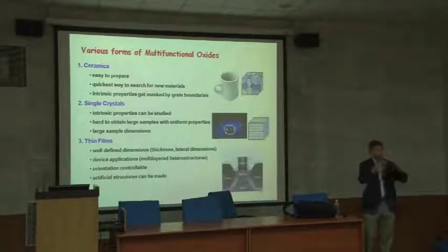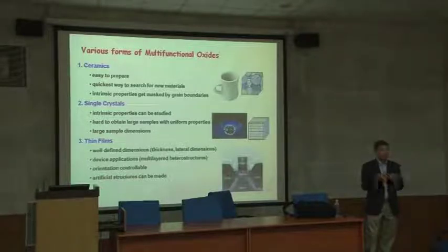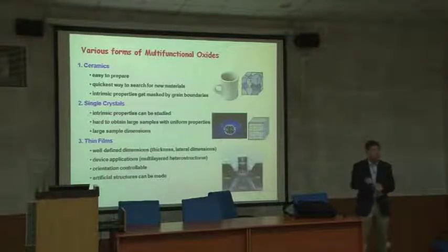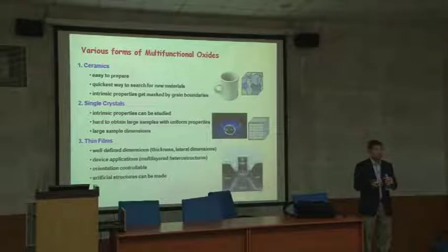And also, when you grow a single crystal, it's preferable to have congruent melting, because when you cool down, you want your material to cool down with the same composition as the melt. But many systems don't look like this. And that's why single crystal growth is very challenging. But a lot of creative single crystal growers make large crystals and high quality crystals to study this.